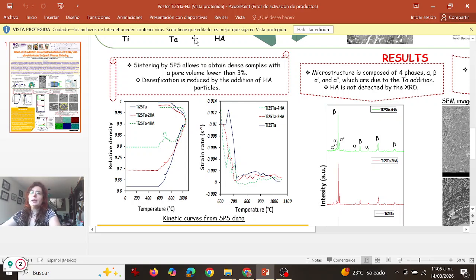As we can see from the curves, sintering by spark plasma sintering allows us to obtain dense samples with a pore volume lower than 3%, and also the densification is reduced by the addition of the hydroxyapatite particles. All right. Okay, let's continue.